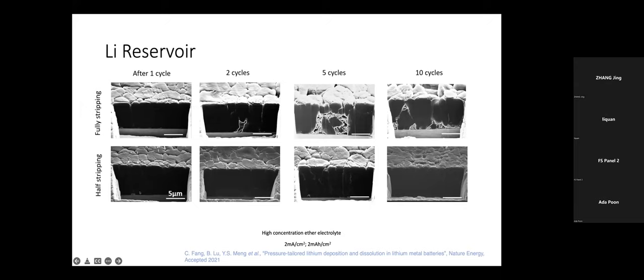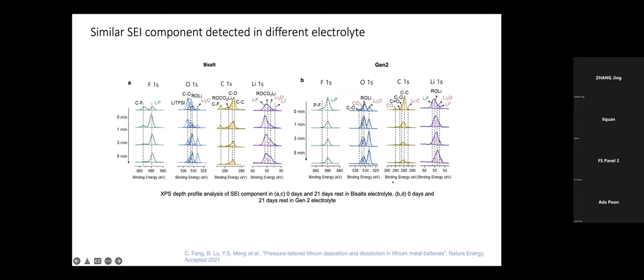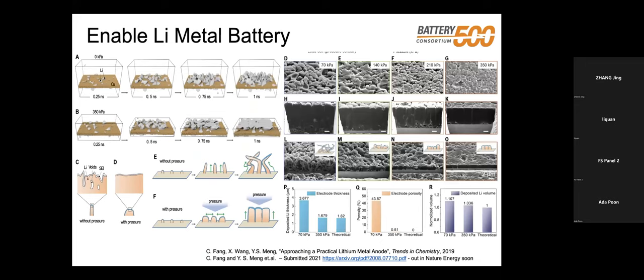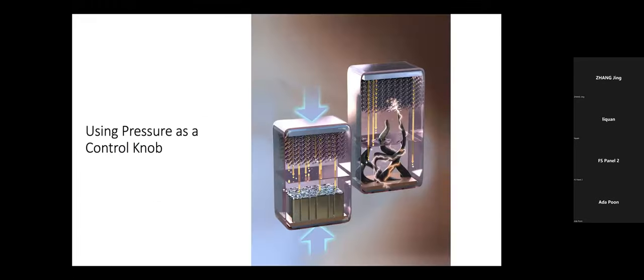And if you always leave a lithium seed layer there, you can go through many, many cycles with good pressure control to actually deposit and strip this kind of dense lithium. And we also provide complementary information to show you the composition from XPS really is the same. There's not much change, right? So this paper is already out in Nature Energy, and I welcome people to read it. And also there is a collaborative modeling work to showcase that lithium metal nucleation really gets impacted by the stack pressure with only around 300 kilopascal.